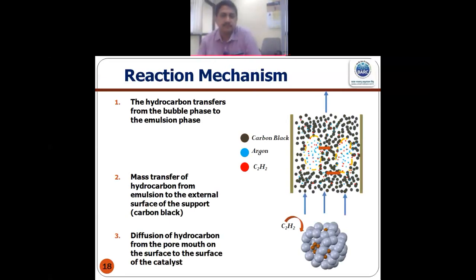Now, after doing this much, what can be the reaction mechanism? If you see this schematic, this is a fluidized bed where there are mainly two phases. One is called the emulsion phase, where gas and solid are homogeneously mixed, and another is called the bubble phase, where the excess gas passes. So what happens at the first step: the hydrocarbon gets transferred from the bubble phase to the emulsion phase, and next the mass transfer of the hydrocarbon from the emulsion has to come to the external surface of the carbon black. These are the carbon black primary particles which agglomerate, and this is a big particle. So this is the transfer of the hydrocarbon from the emulsion to the external surface. Next it goes from the external surface to the internal, where these iron nanoparticles are sitting.